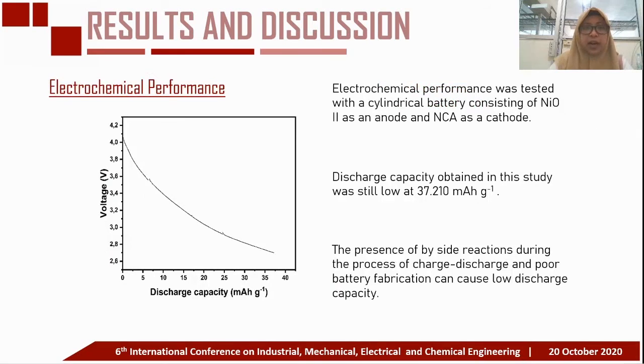And the last, electrochemical performance was tested by a cylindrical battery consisting of NiO 2 as an anode and NCA as a cathode. This test used galvanostatic charge discharge, and the discharge capacity obtained in this study was still low at 37.210 mAh per gram, as shown in the figure. The presence of side reactions during the charge discharge process and the battery fabrication can cause low discharge capacity.